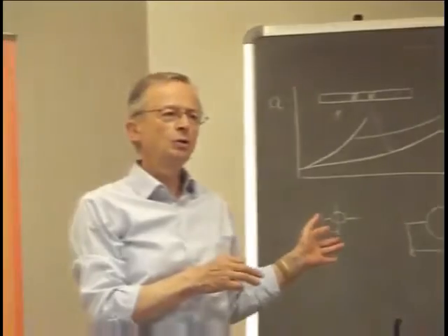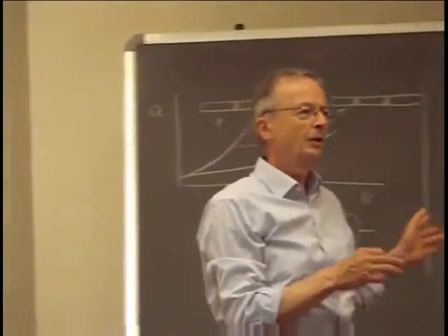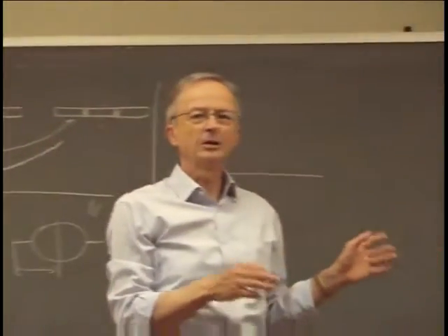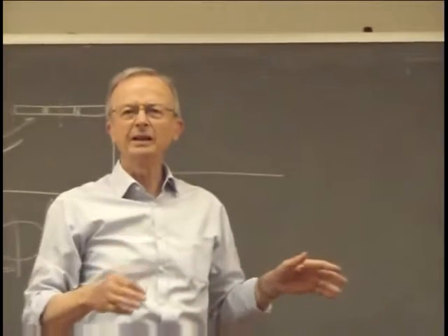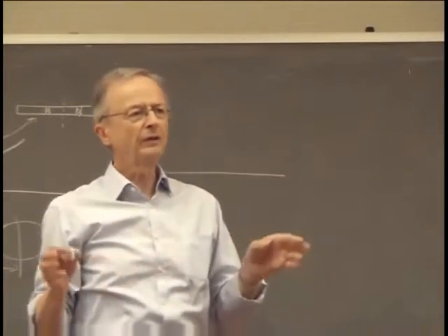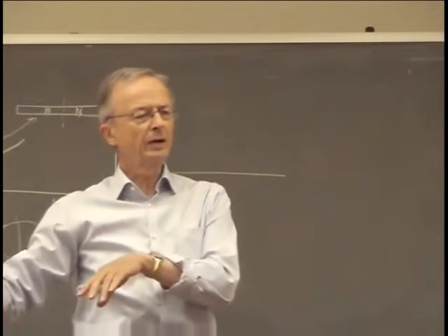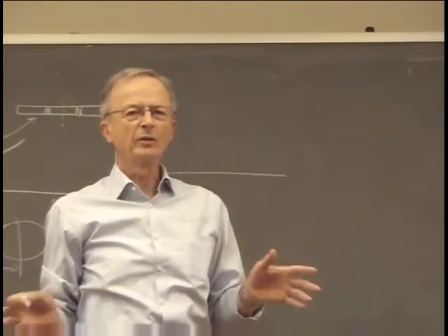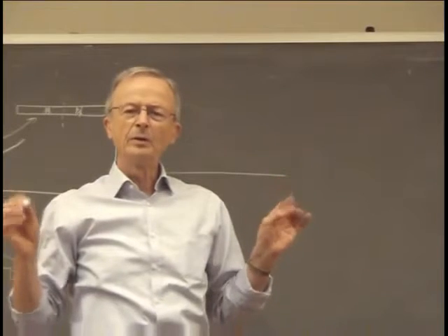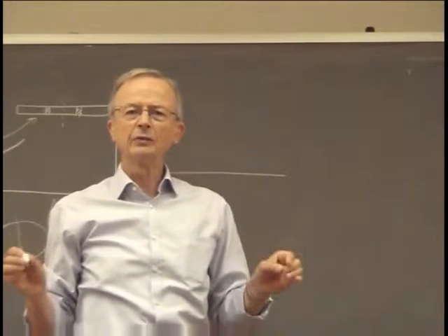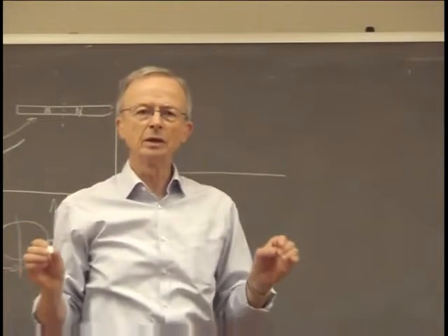Usually when the crack grows longer, the rate increases. But it's easier to show in a diagram to have the crack propagating at a constant rate. This can be easily done experimentally. You control your test machine such that with increasing crack size, the amplitude is gradually lowered, or by a tapered specimen. So we believe we are able to conduct a test with a constant crack propagation rate.